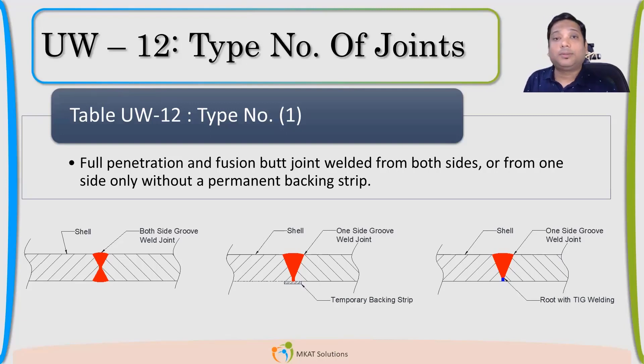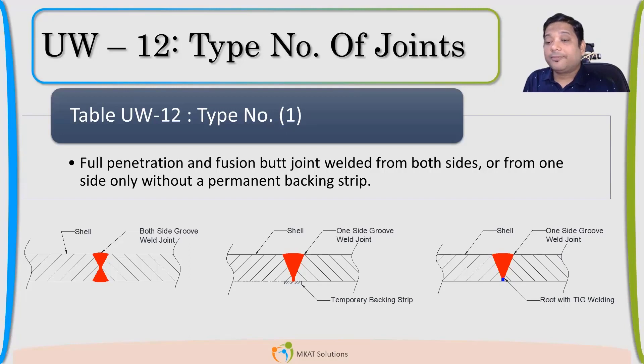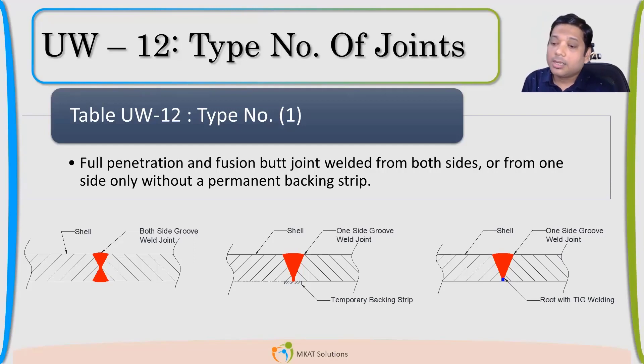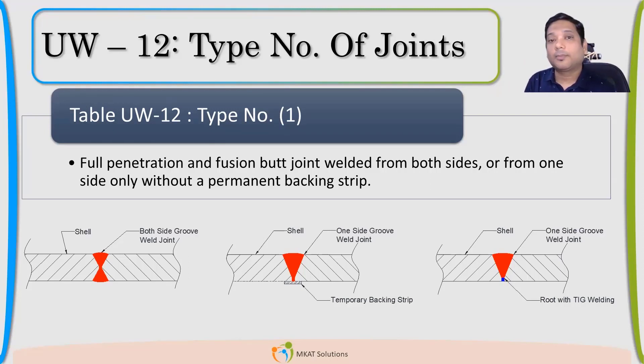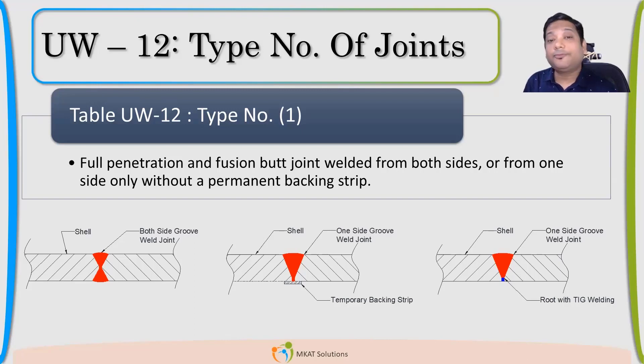If the vessel is very small and it's a closing joint with no manway opening to access inside, or it's very difficult to do the grinding, then we can provide a temporary backing strip. A temporary backing strip provides a base for fusing the root. Temporary means after welding is complete, we remove it — we have to remove it. By using this backing strip, you can also ensure complete fusion of the root and achieve full penetration.